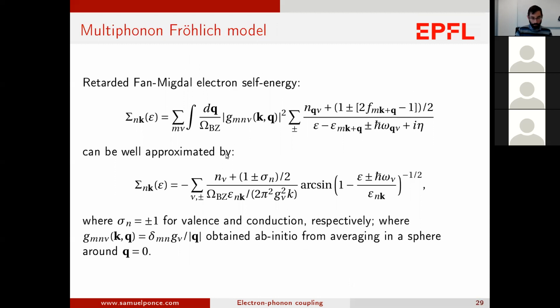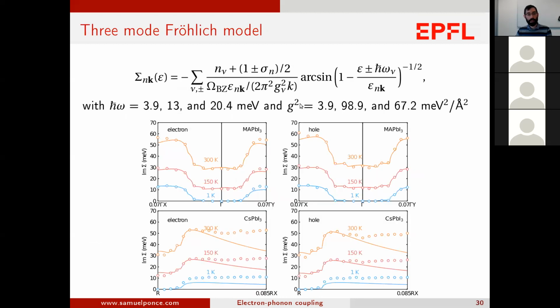And what we can do, and what we've shown, is that one can approximate very accurately this self-energy in the case of MAPI, because there is no acoustic scattering, so because it's only optical scattering dominated. Then we devise this Fröhlich-based model, which of course existed before, but now we sort of extended it to a multi-mode Fröhlich-phonon-based model. And so here, basically in this model, what we have is a sum over various modes. And so in the case of MAPI, we only need 3 modes to reproduce well the result. And so this is what I'm showing here. So this is the imaginary part of the self-energy, which will be needed for the mobility.